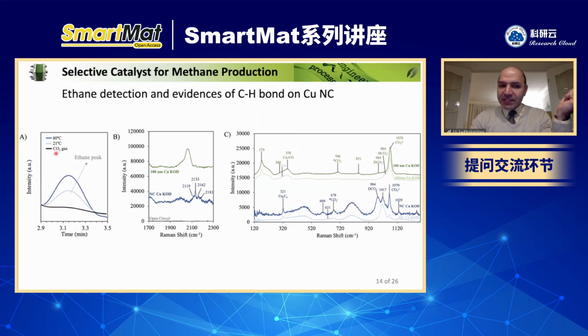So you see in our CO2 gas, there is no impurity like ethane impurity. So this is the GC results. And this is the time that we expect the peak for the ethane. So at room temperature, that's the peak that we get for the ethane. So the amount of the ethane is very small. We can't even convert it to the Faraday efficiency because it's very small, like less than even 0.1%.